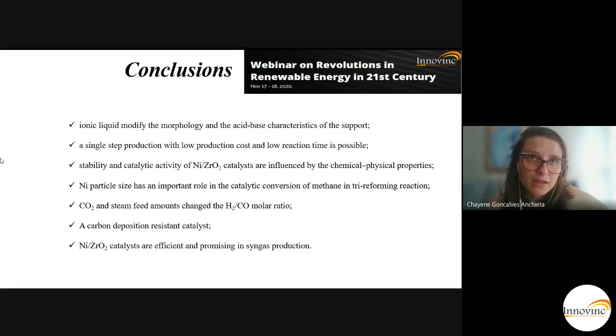So, changing the properties of metal support interaction, we could see which are the most promising catalysts. And if we want to change this molar ratio, we could change the feed to obtain syngas with the ratio that is needed for Fischer-Tropsch reactions, for example. Also, in this type of catalyst, we couldn't see carbon deposition over the surface of these materials. This is due to the higher metal support interaction, and also due to the balance of basic and acid active sites. When we're talking about nickel zirconia catalysts, we are saying that they are a promising catalyst for syngas production and also for the tri-reforming of methane.